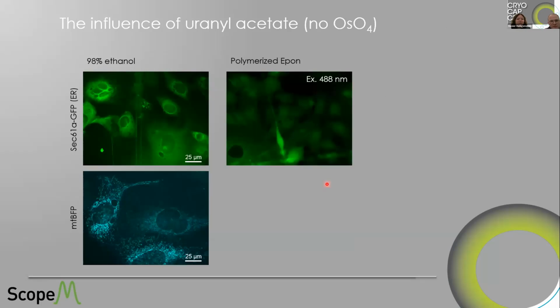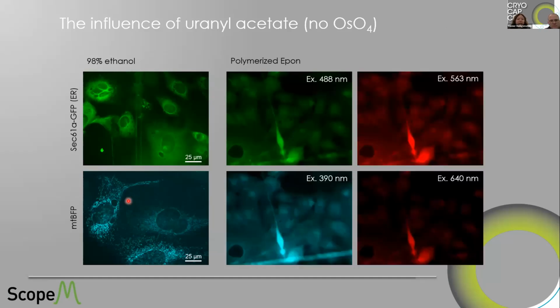This is to highlight the actual influence of uranyl acetate. Just a comparison, same cells, this is still live, and now we have the polymerized samples. And as you see, we do have some fluorescence left, even in epoxy resin. This is now done without osmium, but we do get the same fluorescence signal, basically, with all kinds of different excitations. And only this part is really specific. This is the cell, and all the rest is background. So we should not underestimate the influence of autofluorescence of uranyl acetate, which, on the other hand, can also be used. We have also had studies in the past where we actually used just uranyl acetate fluorescence from the resin-embedded sample to guide us, instead of adding fluorescence by stains.